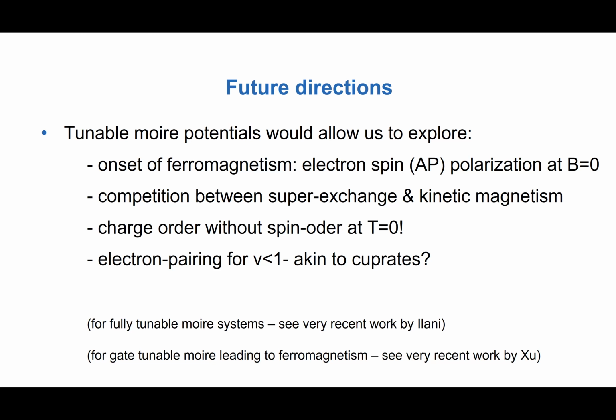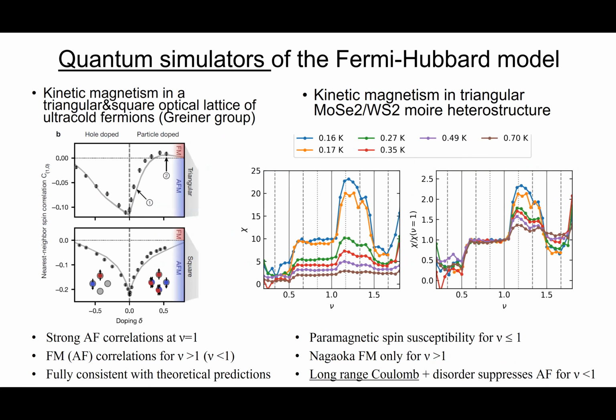So we believe that it's a kinetic mechanism because of this abrupt jump in the spin susceptibility as soon as we go above nu equals one, right? Direct exchange should not be influenced by the presence of a minute but finite number of doublons in this system. That would be my answer. But the point is, why is nu equals one not ferromagnetic, and not antiferromagnetic either? We don't have an answer. The ferromagnetic would be stronger, and they can't compensate partially. I don't know. Okay.